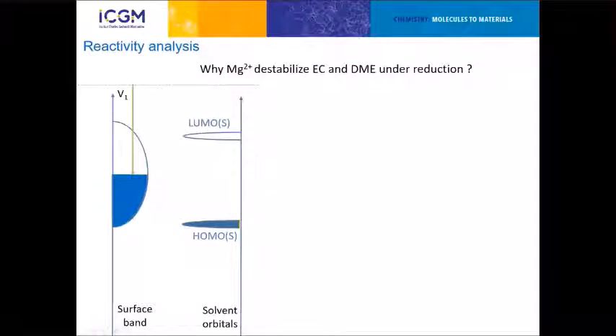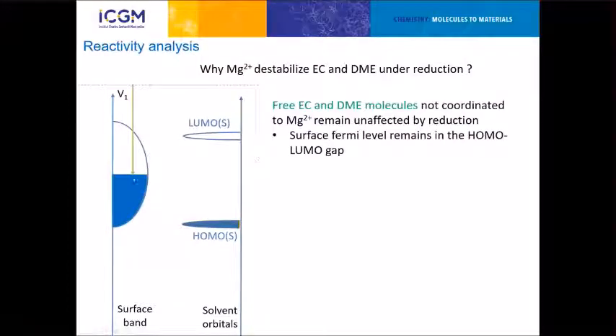So exactly, how can we understand this instability? Actually, this instability is really specific to the solvents that are coordinated to magnesium. If we do this study with simply ethylene carbonate or DME at the interface, we observe no dimerization, no spontaneous decomposition. You really need to have magnesium that coordinates the solvent. So what is happening? In the case of free solvent, not coordinated to the magnesium, just in the electrolyte, the Fermi level of the surface is sitting just between the HOMO and the LUMO of the solvent molecule. So in fact, no electron transfer is possible. There's no reduction that can occur.